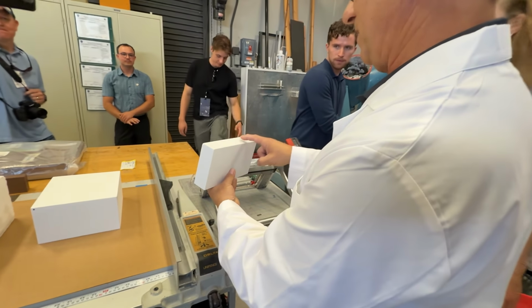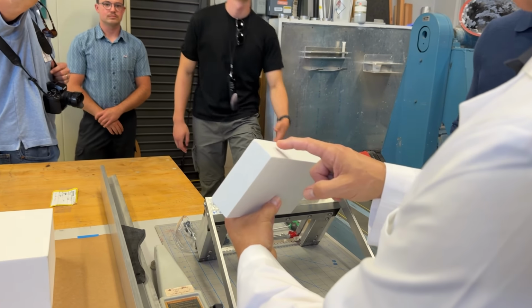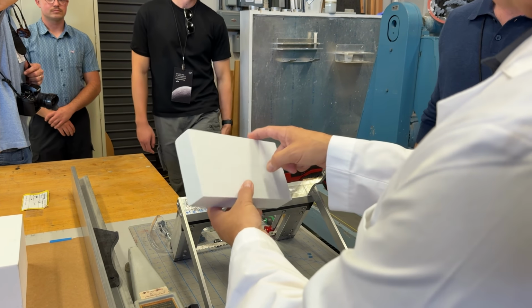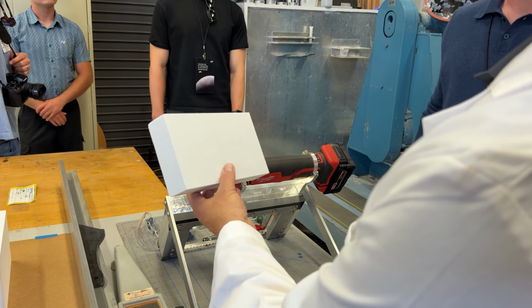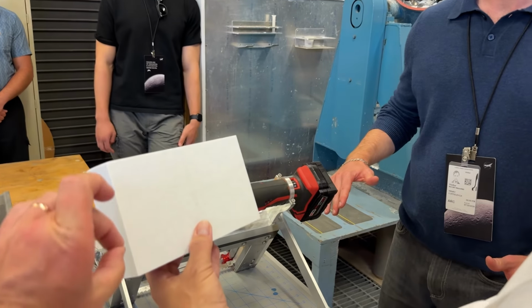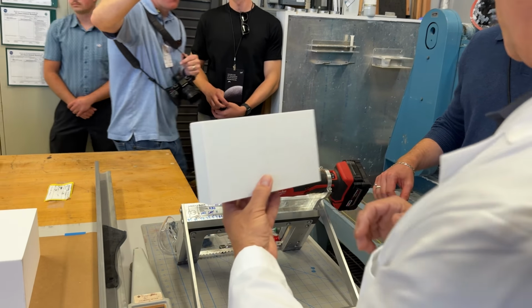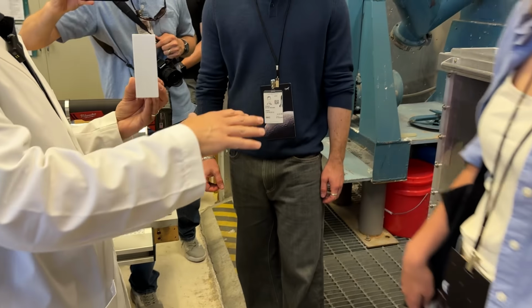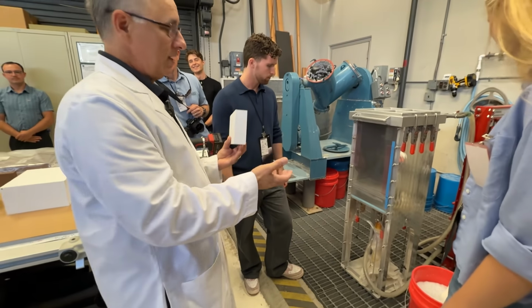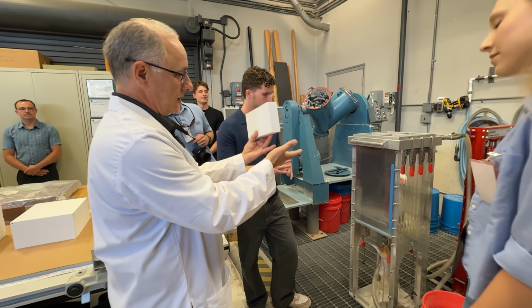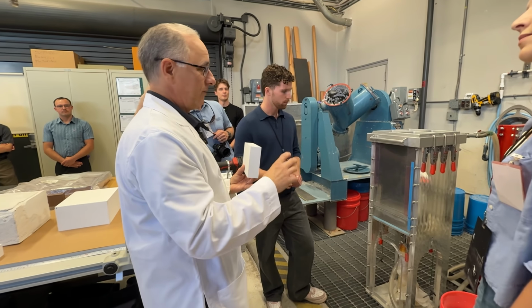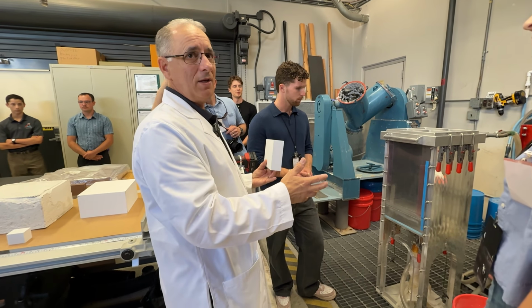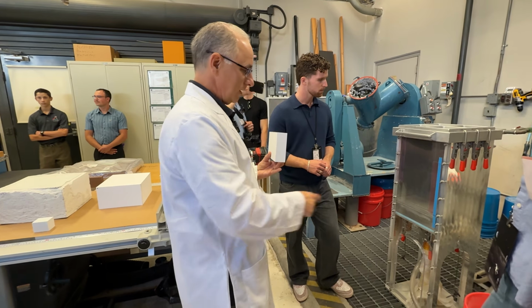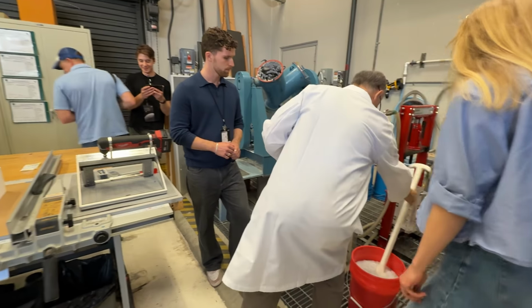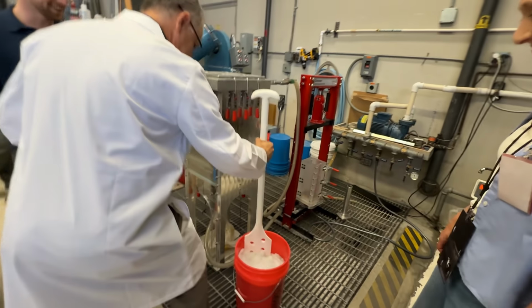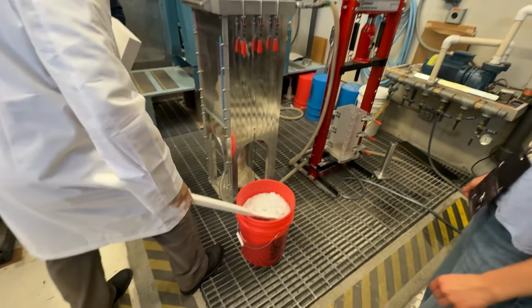If you look at this, this would be the top surface that has the 12 on it. You don't really see a fiber direction. Sure. But if you look at the side, you can see the fiber lay is horizontal. So was it compressed in this direction? It was compressed in this direction. So when the fiber goes in this casting tower, and the water is drawn off the bottom, the fibers will settle on the bottom and they will lay horizontally. If you draw it off at the right rate... if you try to go too fast, you don't get the right fiber lay. And so here's a bucket if you wanted to give it a stir to see what the large mix looks like. It's really high tech.